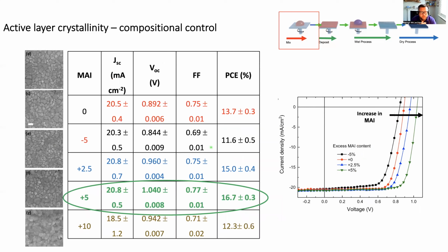What is important, and here I can just summarize some device performance parameters. Despite the previous data showing this continuing increase in crystallite size, here we see the largest grains along with the 10% methyl ammonium lead iodide. The corresponding films actually perform relatively poorly, and in fact here they perform worse than the reference cells. So again, the idea of roughness and coarsening has a detrimental effect.